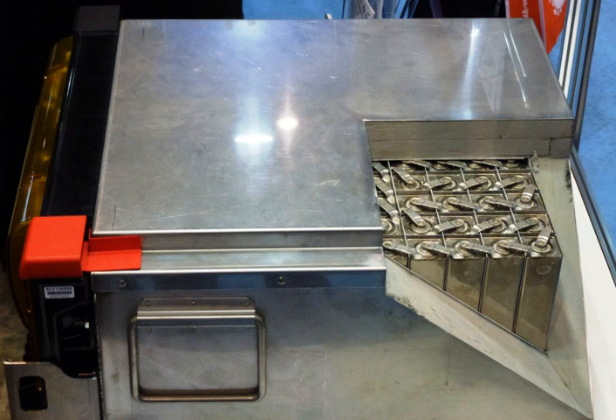One design uses a fuse strip containing barium chromate and powdered zirconium metal in a ceramic paper along the edge of the heat pellets to initiate burning. The fuse strip is typically fired by an electrical igniter or squib by application of electric current. Another design uses a central hole in the middle of the battery stack, into which the high-energy electrical igniter fires a mixture of hot gases and incandescent particles. This allows much faster activation times — tens of milliseconds versus hundreds of milliseconds for the edge strip design. Battery activation can also be accomplished by a percussion primer, similar to a shotgun shell.